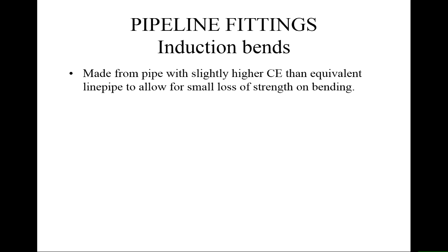How does that work with overmatching? Are you overmatching the carbon equivalent or the strength of the pipe? You're overmatching the strength of the pipe in these cases rather than the carbon equivalent. So you want to know what you've got left in the way of strength of that pipe after induction bending. Now, it may be that if you control the induction bending process correctly, that the ends of those induction bends have the same properties as the line pipe, but they will have a slightly higher carbon equivalent, therefore your welding process would have to be adjusted accordingly.